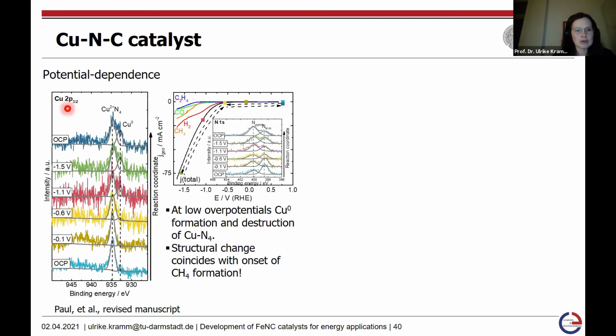Here we have the Cu 2p spectra, and here it is the N1s spectra. And to make a long story short, in both spectra, you can basically see the transformation, at least of part of the Cu-N4 centers to the metallic state. So this confirms the already existing data. But what is quite interesting to note is that this structural change coincides with the onset potential for the methane formation within this catalyst material.